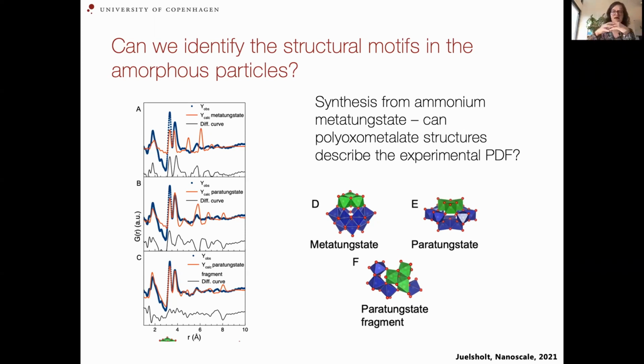So that's what we gain: we can get a motif that will dominate in the local ordering of the nanoparticles. And in similar ways, we can characterize a lot of nanomaterials, and therefore be able to correlate this synthesis, structure, and properties relationship.